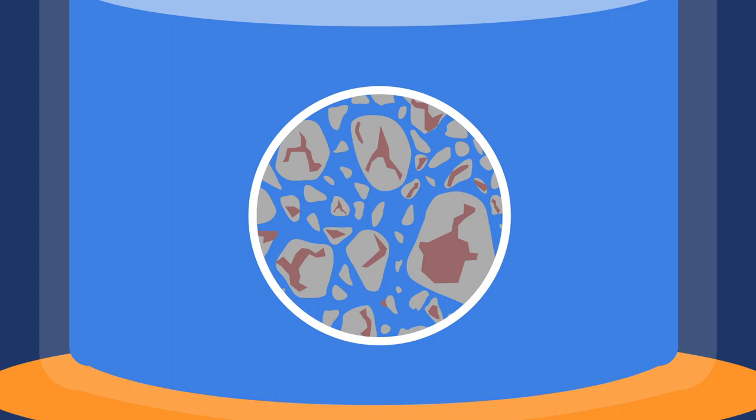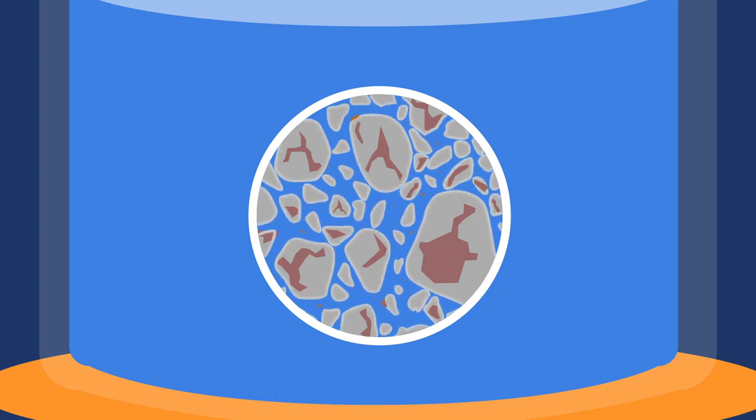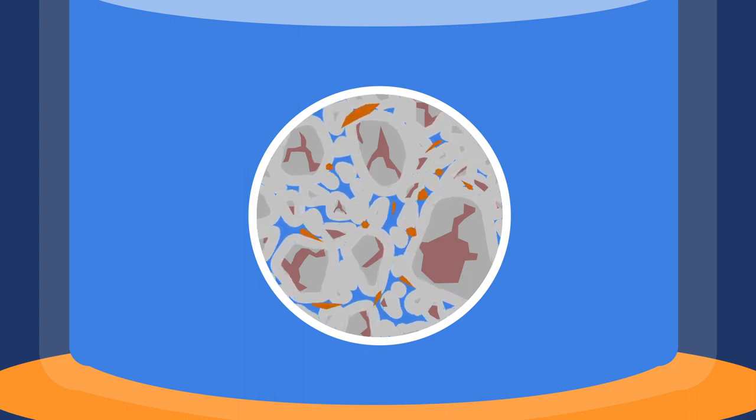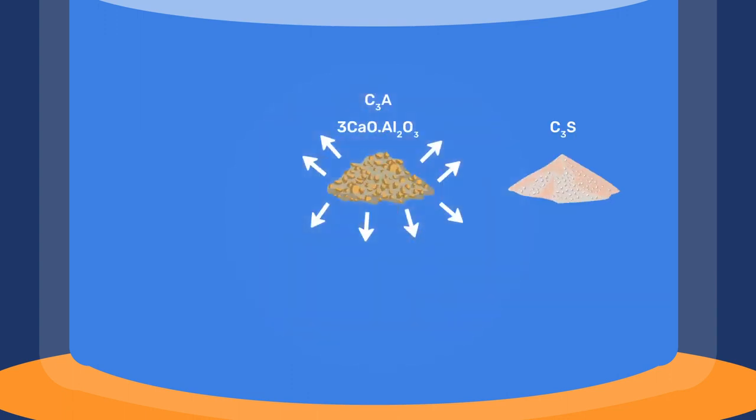An important aspect of cement hydration concerns tricalcium aluminate, or C3A. While this phase is typically intermixed with C3S and/or other clinker phases in cement grains, we will represent it separately for didactical purposes. C3A reacts initially very fast with water, producing AFm phases and releasing aluminate ions into solution.